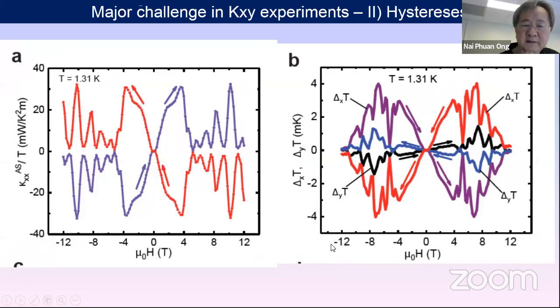Okay, so going on to the thermal Hall effect, when you go below 4 Kelvin, and this possibly was the reason that the Kyoto group stopped their experiments there, you start to see enormous hysteresis. As an example, we're showing here the thermal Hall signal, the diagonal conductivity signal measured with the field swept from left to right in blue, and then the return sweep from right to left. And you can see that there's a huge amount of signal. This is what we call the anti-symmetrized curve, right? So we have taken the forward sweep and the reverse sweep and anti-symmetrized them in a futile attempt to get rid of the hysteresis. So you can sort of see the kinds of experimental challenges.